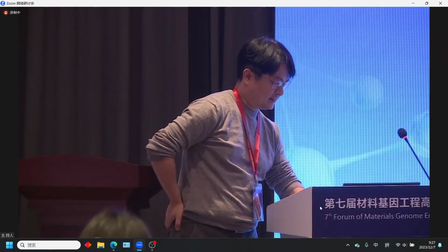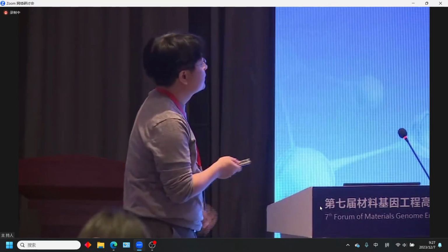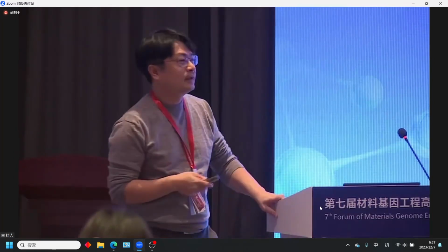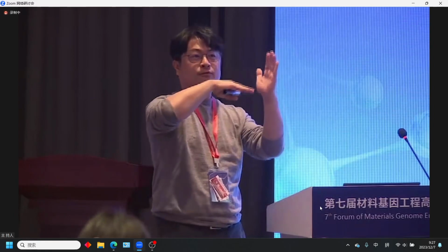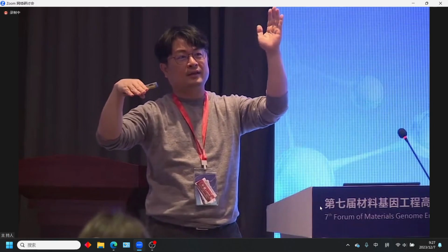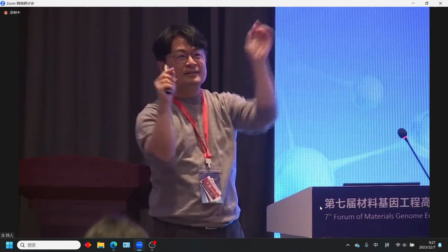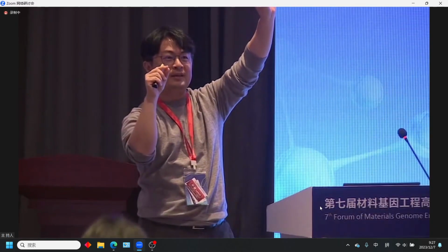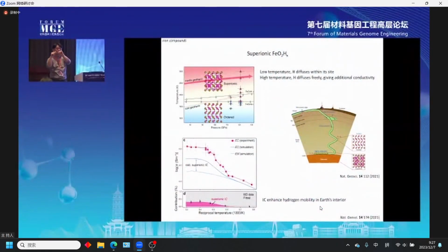Sorry. So I showed one graph of reciprocal temperature versus conductivity, combined with the experimental data. In a certain temperature range there was an enhancement of conductivity, shown by the experimental data as dots. I can show you later. Okay, this one. So this is the experimental data at high pressure, and this is our calculation data. This is when we consider only electrical conductivity, and this is when we combine it with ionic conductivity as well. There is an enhancement here, which is also a good match with the experimental data showing a sudden increase of conductivity. So we believe this is the first evidence of superionicity of this iron oxyhydride.